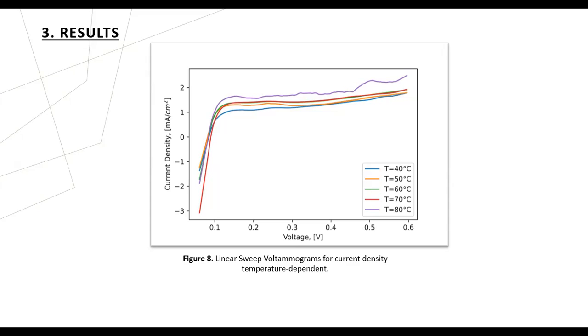Water comes from the humidification of the gases, which when passing inside the PEFC produces water condensation. The water absorbed in the membrane lengthens the polymer chain, which produces an increase in the volume of this, allowing a greater diffusion of hydrogen.